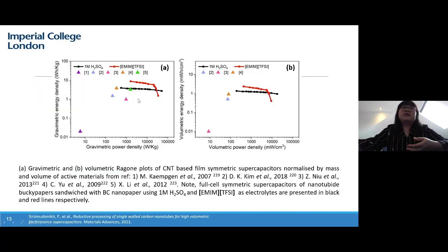To compare the performance with other CNT-based symmetric bucky paper cells in both gravimetric and volumetric performance, I plotted the Ragone plot, normalized by the mass and volume of the electrode materials. It shows that both the 1 molar sulfuric acid and the ionic liquid cells present a higher energy density and way better gravimetric and volumetric power densities compared with other cell devices in the literature.